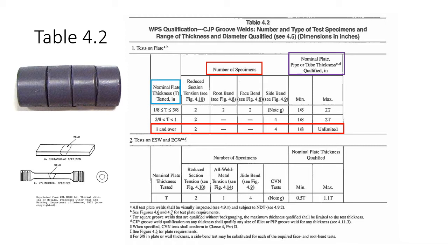That's kind of a cheesy picture, but I pulled it out of a military manual. So we got to do 2 tensiles, and then we don't have to do any root bends or face bends because the material's too thick. So we're going to do side bends. So we got to do 4 side bends. And there's a picture with our 4 side bend tests bent there. And then under the purple, it tells us the nominal plate or pipe or tube thickness that we're qualified. So we can weld everything between 1/8 of an inch and unlimited. So that's how you read that table.